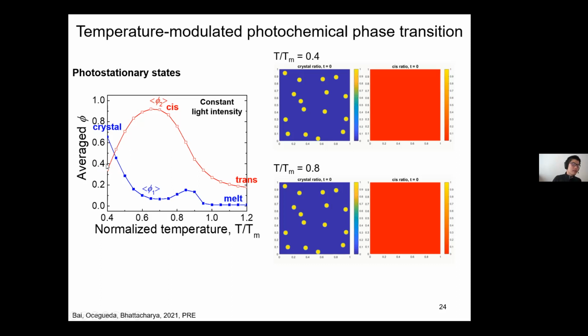Trans is more periodic. Now, if I increase my temperature, these crystals will tend to melt more, right? So I will have less and less crystal. But at the same time, when the crystal melts, I have a photoreaction, so trans becomes cis. So my cis ratio increases until it reaches a peak. But now remember, if my temperature is increased too much, I will have a backward thermal relaxation from cis to trans. Now you see that they are in competition with each other. So after reaching a peak, the cis ratio becomes lower and lower. And then there might be a recrystallization because the temperature is still below the melting temperature. So you have a very interesting non-monotonic behavior, depending on the temperature, in this material.